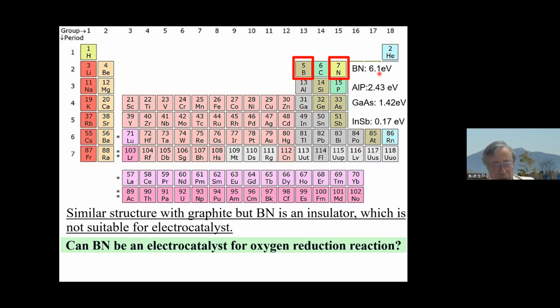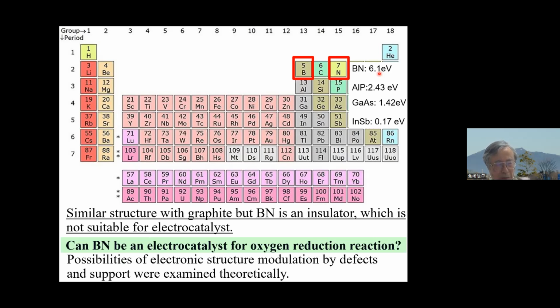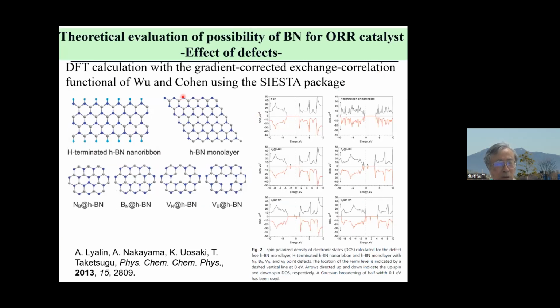Can BN be an electrocatalyst for oxygen reaction? People say no. However, there's a possibility of electronic structure modulation by defects and support. So we did the first theoretical calculation for the possibilities. We calculated various types of boron nitride, introducing defects first.